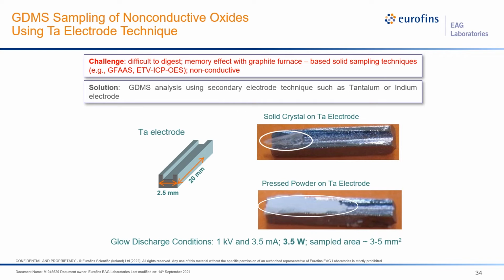There are challenges with this high purity alumina analysis. It is difficult to digest, so solution-based techniques often have a lot of issues. It has a memory effect if we're using graphite furnace-based techniques, because alumina will react with graphite, creating a lot of roughening of the surface and hence the memory effect. In standard GDMS mode, because this is non-conductive, it doesn't work. EAG came up with a secondary electrode technique using a tantalum or indium electrode to allow this analysis to happen. Here is how a tantalum electrode works: basically it is a pin, we create a groove, and on top of it we put a solid crystal or powder pressed on it, and it allows us to do the analysis.